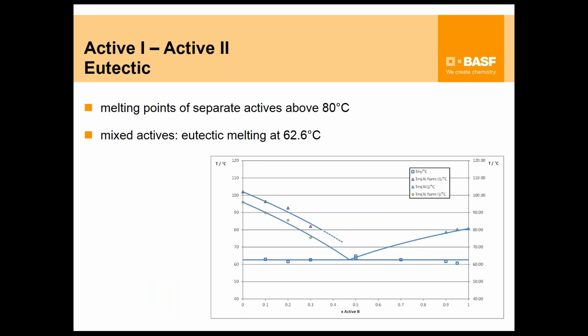And here is the phase diagram of mixtures of active 1 and active 2. On this line, you see the properties of active 1. On this line, you see the properties of active 2. What I did here, we did lots of DSC runs, and I plotted the DSC measurements in this phase diagram. Just to have a look at this, I have my active 1, and when I increase the temperature, I observe melting of my active 1. And in this case, I also see melting of a second polymorph of this active 1. So up to here, I have a solid. Here I have liquid, recrystallization to the second polymorph, and then melting of the second polymorph, and then here I have a liquid.